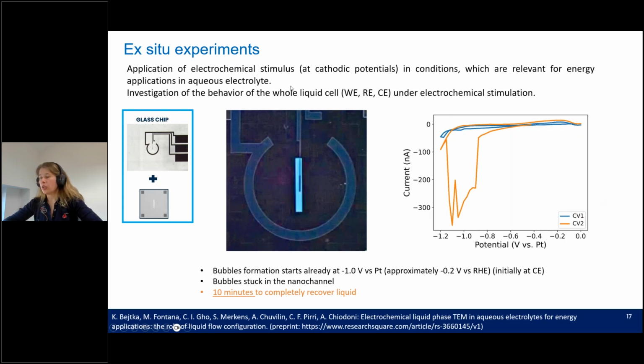I show you the first experiment where the glass chip is paired with the standard small chip, and we will investigate the behavior of the whole cell under the provision of cyclic voltammetry stimulus. The cyclic voltammetry in the range between 0 and minus 1.2 volt versus platinum, and I will run this video now, and we can observe that there is the formation of the bubble here at the counter electrode at approximately minus 1 volt. And then I will play it again.